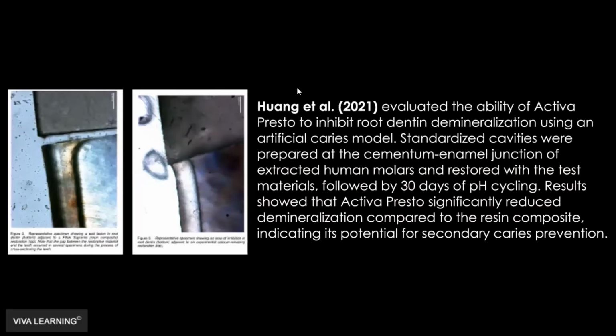This was our study from Chenta Huang, who was one of the residents in my program, who's awesome. Chenta did the study where he got extracted teeth and put fillings in contact with the root dentin. And then he put in an artificial caries model. We didn't use bacteria, we just used acid. So we did 30-day acid solutions, 30 days on and off with acid. And then he sectioned them and looked at the interface of the restorative material. So in these two pictures, the top part is the restorative material and the bottom part is the root dentin.